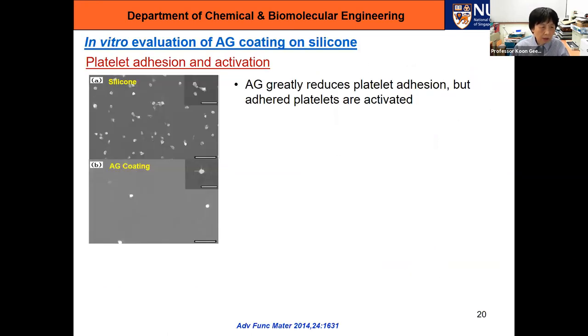So this is our data with platelets. So again, the top image here is the silicone surface, and you can see platelets adhering. And this is after the agarose coating. It looks good in the sense that it reduces the number of platelets very significantly. But if we look very closely at the platelets, we see the presence of pseudopodia. That means these platelets are still activated. So this will not do for blood contacting surface.